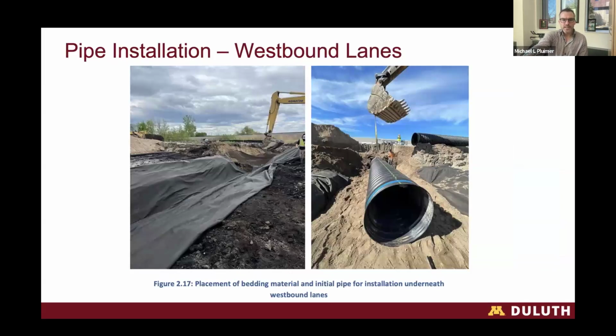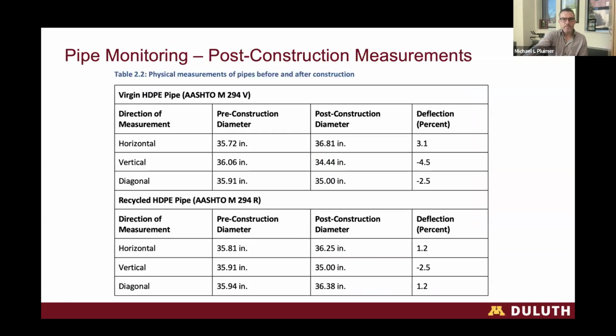We then did the westbound lanes, and in this case, we had to make sure our sensors were lined up appropriately with the traffic loading. Then we recorded some deflections both pre and after installation, and you can see our deflections were reasonable there, a little bit greater on the virgin pipe than the recycled pipe, showing 3 to 4.5% of deflection after construction. This was before the final pavement. And the same thing on the recycled pipe was about 1 to 2.5%.